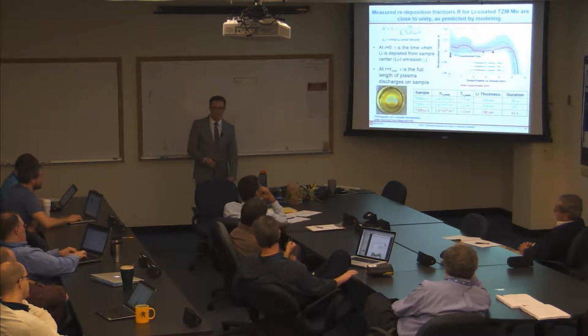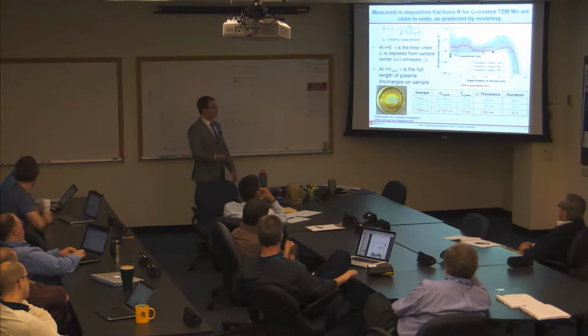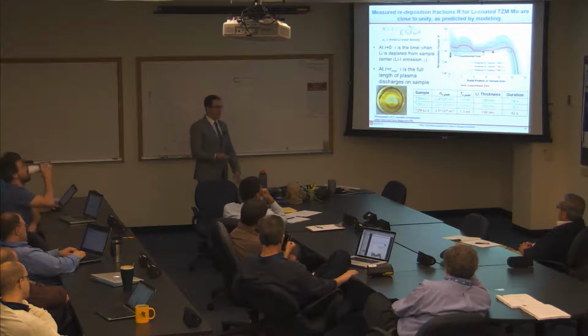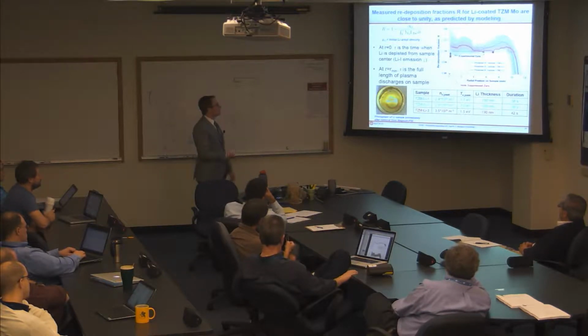And it turns out that the fluence of lithium that you get off of the target is actually much, much larger than the initial areal density. And this is because of redeposition, or this is assumed because of redeposition. So your inferred R is 1 minus the areal density divided by the total fluence. And so those are these measurements here.